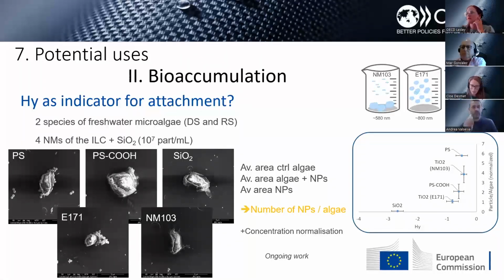You can see here on the graph the hydrophobicity index presented as a function of the number of particles per algae that was measured. These first results look promising, with clear differences between hydrophobic and hydrophilic material, and there is a trend between the two parameters, but this study is ongoing and we have to evaluate more material.